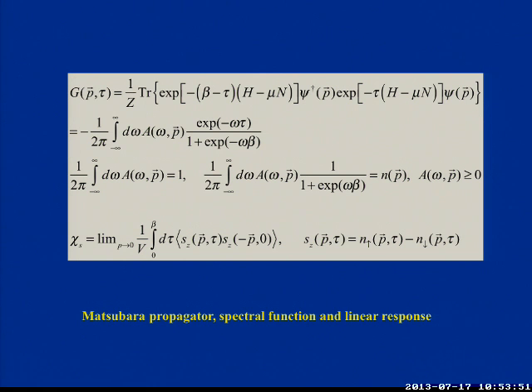Theory, what we do. In order to calculate various properties I'll be talking about, we'll need to calculate the Matsubara propagator. I think everybody knows what that is. That's related with the spectral function. We calculate this, we have to know this. And you see there is a problem, because this is known in a finite time interval, imaginary time interval. So if I want to do the inverse Fourier transform or something, it will be a problem. In order to do this, we apply 2 methods, maximum entropy method and singular value decomposition. I'm not going to say much about this. We know from theory that it satisfies certain restrictions. Integrates to 1, integrates to particle number, and it's always positive. When we do the determination of that, we use these constraints, and then we invert this integral operator to find this quantity. Okay? We calculate in particular spin susceptibility, viscosity, and a few other things.